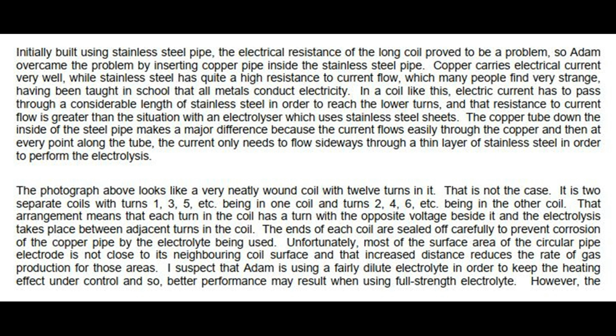The ends of each coil are sealed off carefully to prevent corrosion of the copper pipe by the electrolyte being used. Unfortunately, most of the surface area of the circular pipe electrode is not close to its neighboring coil surface, and that increased distance reduces the rate of gas production for those areas. I suspect that Adam is using a fairly dilute electrolyte in order to keep the heating effect under control, and so, better performance may result when using full-strength electrolyte. However, the HHO production at around 16 amps looks impressive, as shown here just before the whole container is obscured by the HHO bubbles coming off the coils.